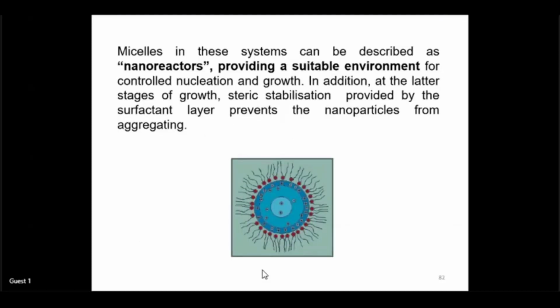And micelles in this system can be described as nanoreactors, providing a suitable environment for controlling nucleation and growth. In addition, at the latest stage of growth, steric stabilization provided by the surfactant layer prevents the nanoparticles from aggregating. So it's very important. They should not collide with each other, otherwise it will make a large droplet. So the reaction in water or oil is very important, depending on whether you are using the micelle or reverse micelle technique. Fine.